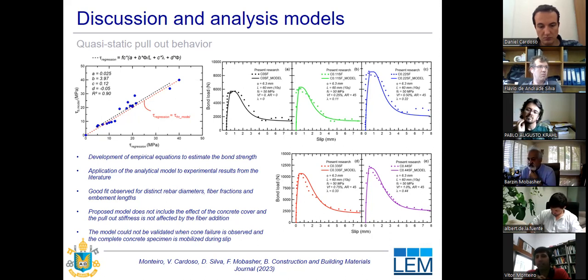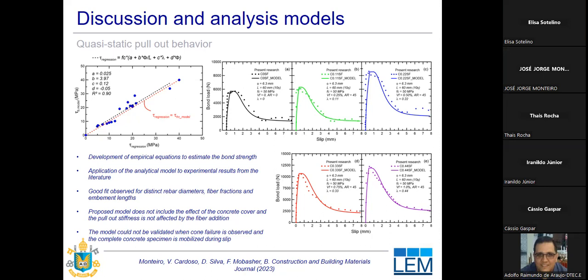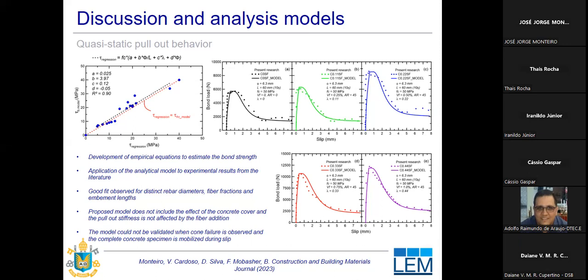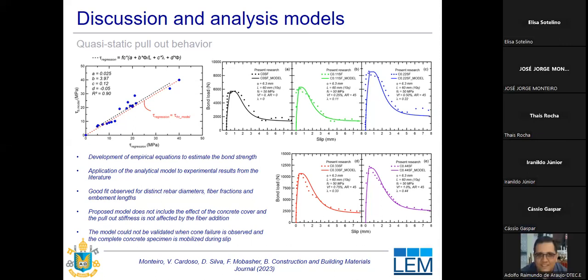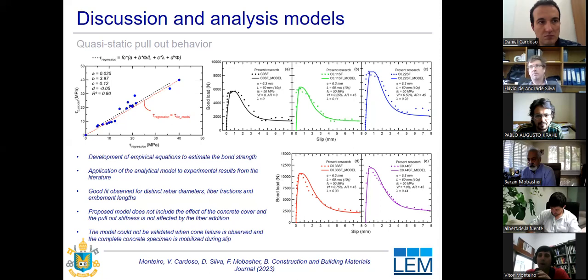A second limitation is based on the type of failure. This model is assuming that we have an interface degradation. That means only a small ring of concrete is mobilized during the pull-out. So we have an almost perfect pull-out of the rebar with the presence of really small cracks on the top surface when the rebar is being pulled out from the matrix. So this is also a limitation because sometimes we can verify very large cracks in this kind of test.